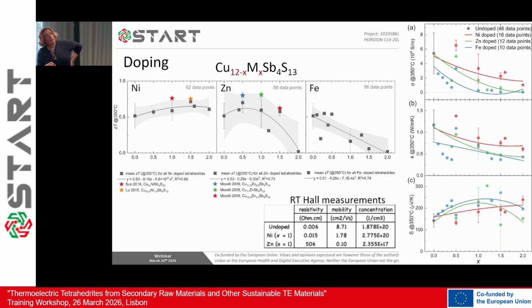And when you try to see the electrical conductivity, thermal conductivity, and Seebeck, you see that iron is really the one that decreases mostly the electrical conductivity. The thermal conductivity decreases for all of them, again more for these ones than for nickel. And here you see that nickel seems to always be increasing the Seebeck, and these ones might have a maximum.